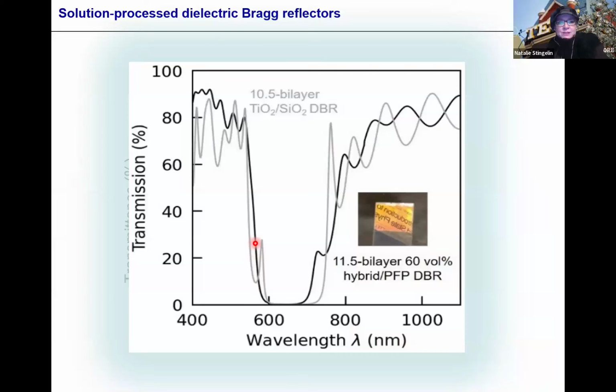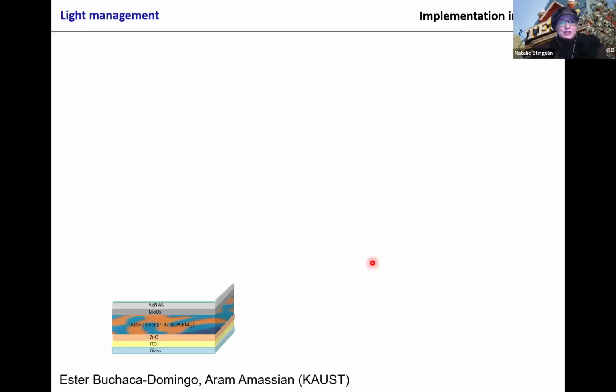And this is important because once we make mirrors, here we had 11.5 bilayers, so that means 23 layers solution processed. This is the black curve, and we compare it with a more standard conventional sputtered mirror, also in gray. You see we get essentially the same performance with essentially the same number of layers. So we knew we can actually really get good photonic structures.